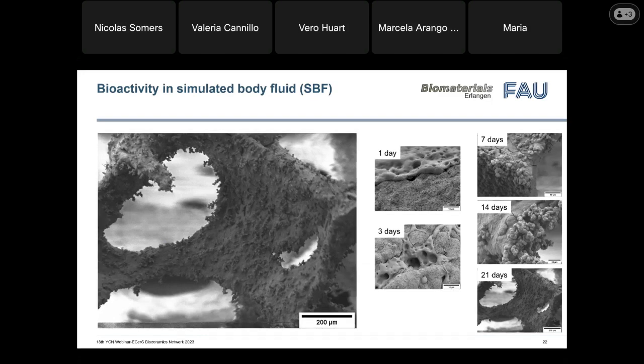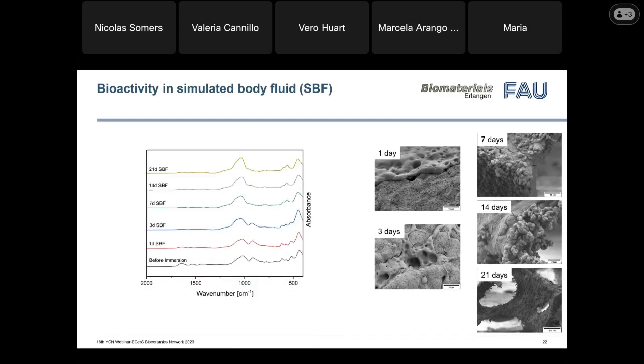And here I also showed the FTIR evaluation. In it, first we have the peak corresponding to the formation of this silica-rich layer, and then also the characteristic peaks of the phosphate groups.